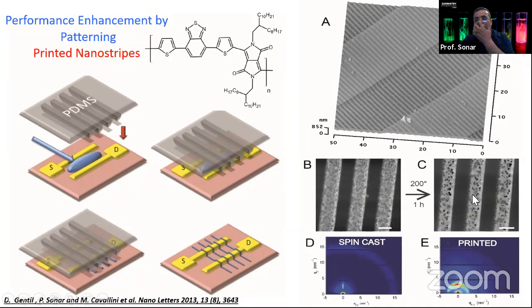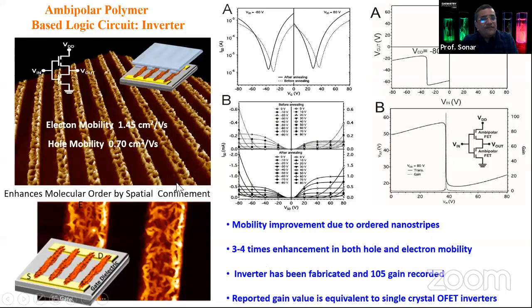And these are some of the X-ray data showing how the crystallinity changes upon annealing. And what we did, we connected the two transistors together, and then we got this inverter using organic-based transistors. So the electron mobility and hole mobility of this particular polymer, upon doing the nano strips, we can enhance: electron 1.45 and hole mobility 0.70. See, for the same polymer, which we published in Advanced Materials, we got mobility of 0.40 and 0.35, just by doing the simple processing engineering. Here we enhance the electron mobility 3 times and the hole mobility 2 times.